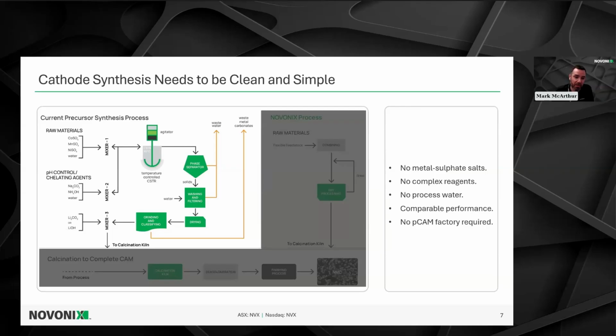So within your reaction vessel, you precipitate out your precursor. All of those metals in the metal sulfates combine to make an intimately mixed metal hydroxide. And that is your output. However, your output still contains water, it still contains some waste. There are a few unit operations that have to be done before you can actually utilize your PCAM, your NMC hydroxide in this case. There are washing and filtering steps, which require additional water and generate further wastewater streams. And you're also making a few heavy metals along the way that need to be carefully considered before discharging into the water table. Eventually, you end up in a state where you have a PCAM powder, an NMC hydroxide, typically.